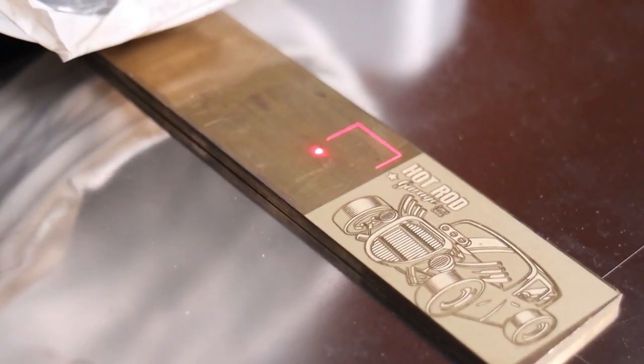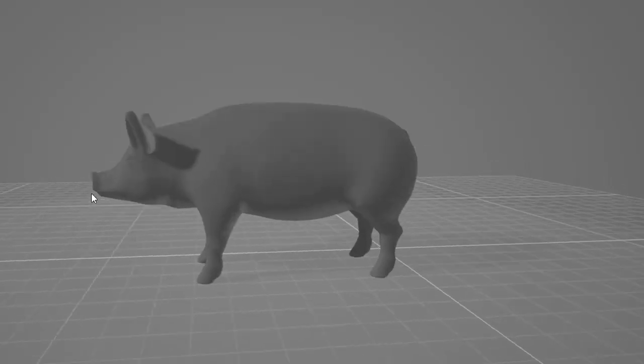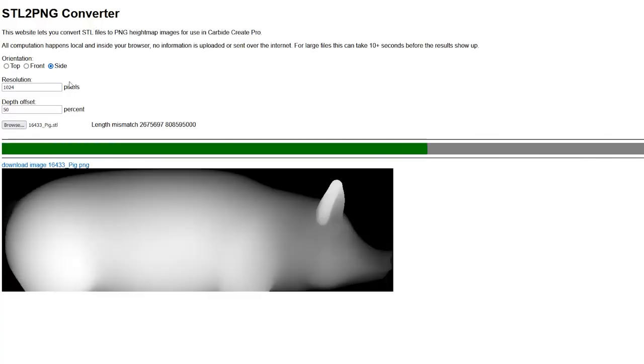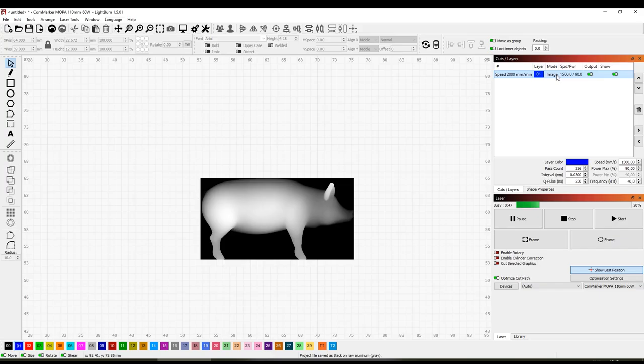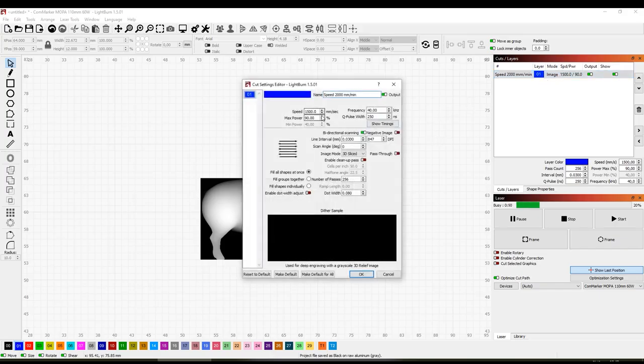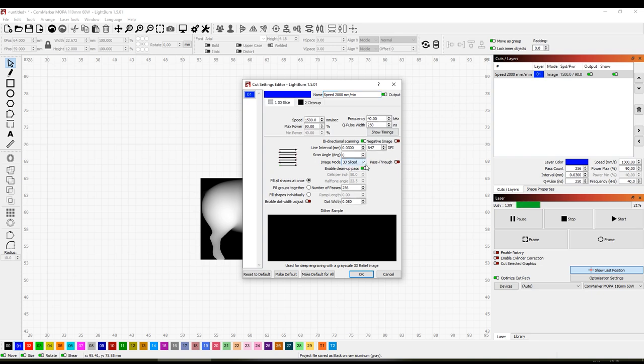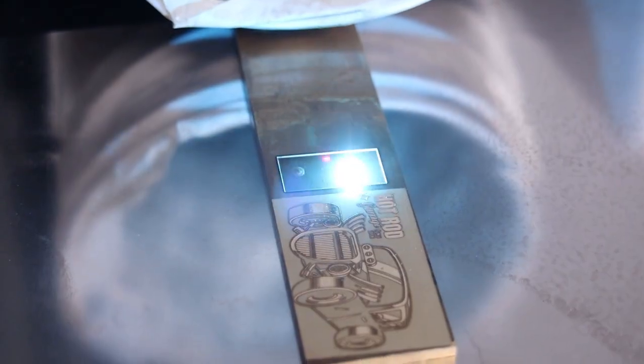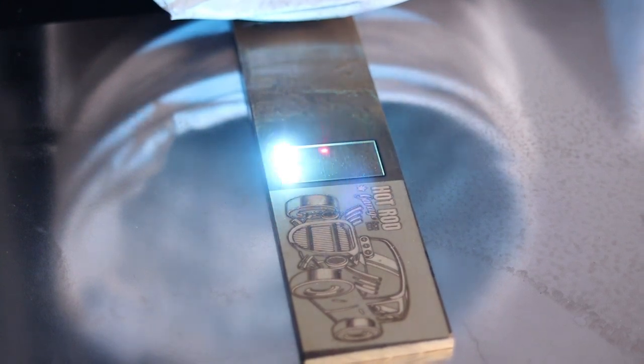After seeing how well the Commarker engraved that coin, I was curious to see how deep you can really engrave with this machine. As I wanted to try out the 3D engraving feature, I have converted a 3D model of a pig into a grayscale image using an online converter. 3D engraving works in a way that the darker the shade, the more passes it will run for that part and the deeper it will be engraved. When setting up the 3D engraving, you should always set up 256 passes, as this is how many shades of grey the grayscale image contains and will produce the smoothest results. If you want to engrave deeper, you should increase the number of passes by 256 each time. I have also added a cleanup pass after every 10 cutting passes to clean up the surface. I chose aggressive cutting settings, which remove a lot of material and produce a lot of interesting noises.